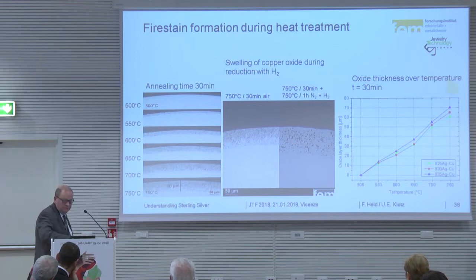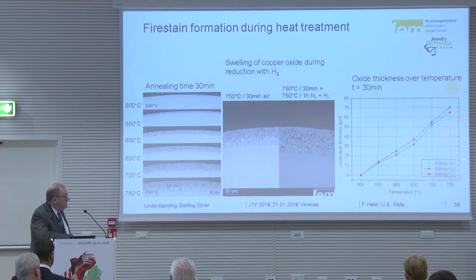And the oxide thickness, you see here, oxide layer thickness in microns with temperature. And it's so that the 935 gets a little bit deeper than the 925, but what's happened is we have here less copper, so the copper oxidation goes faster in the depths.